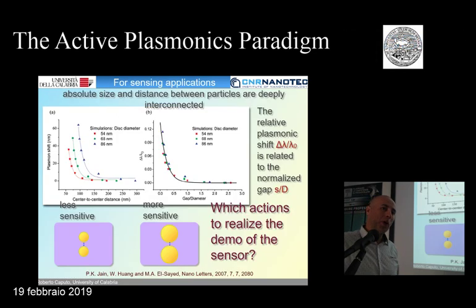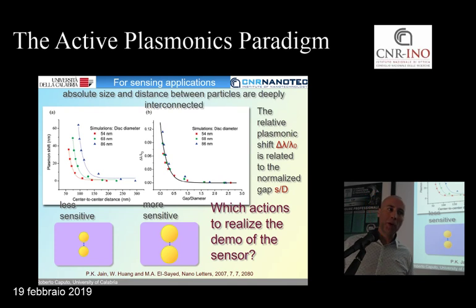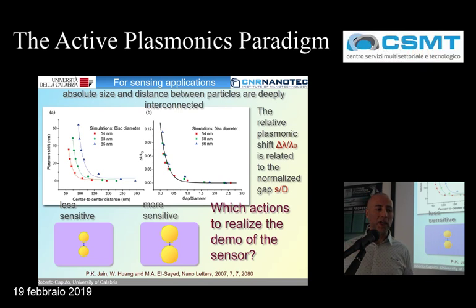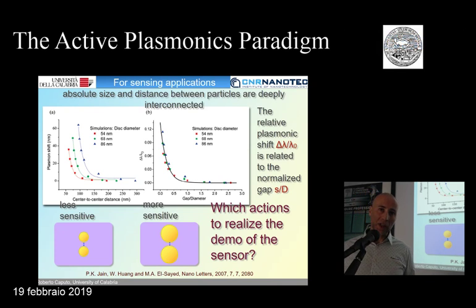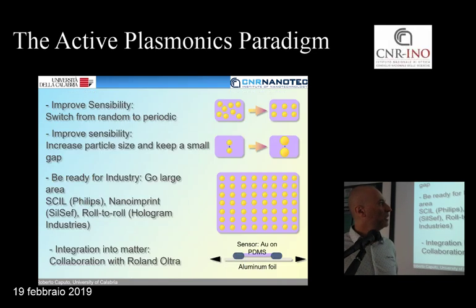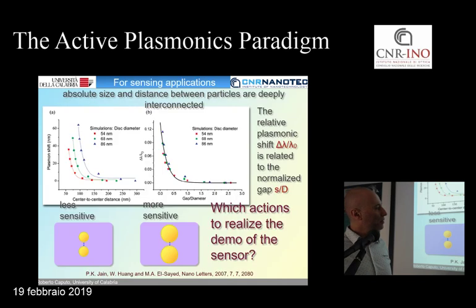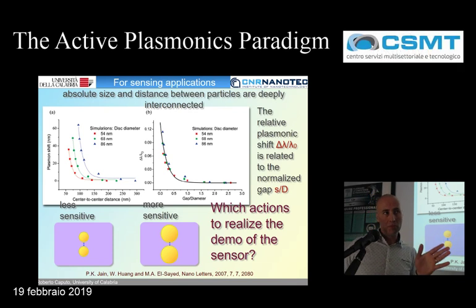Okay, so how to use this? The first idea you get is to make a kind of deformation sensor, a tensile sensor. So the point is about the sensibility of this system, because when we showed the experiment, we used 20% of elongation, which is quite large for a sensor. So if you want to improve the sensibility of this sensor, or this material as a sensor, you should apply some possibilities like, first of all, change the initial size of the particles, because the plasmonic field will be longer range and you have a better sensibility.